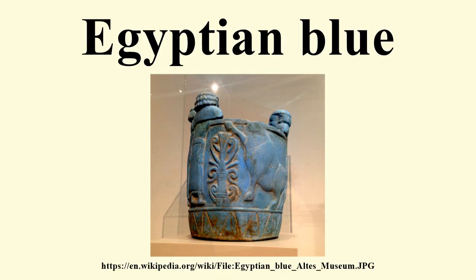Diluted light blue, though, is used to describe the color of fine-textured Egyptian blue that has a large amount of glass formed in its composition, which masks the blue color, and gives it a diluted appearance. It depends on the level of alkali added to the mixture, so with more alkali, more glass formed, and the more diluted the appearance. This type of Egyptian blue is especially evident during the 18th dynasty and later, and is probably associated with the surging glass technology at this time.